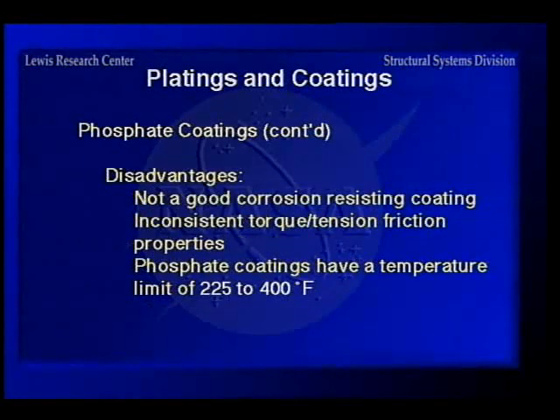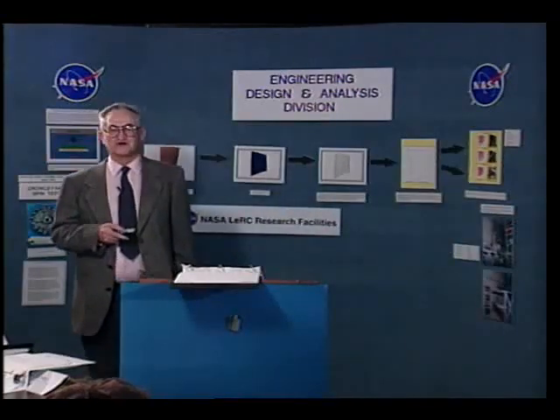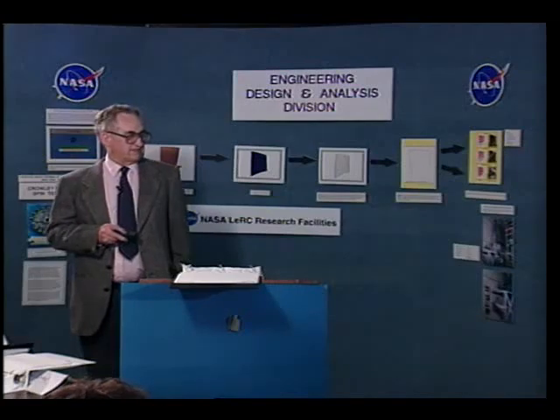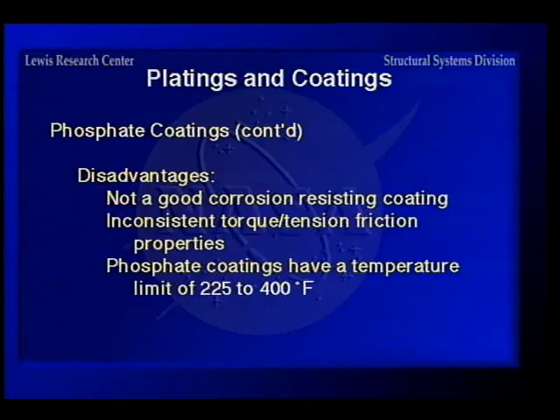But the disadvantage is it's not very good in corrosion. You get inconsistent torque tension friction properties, which means if you are supposed to torque a head bolt to exactly 2,000 pounds tensile load, you don't know what torque it'll take to do it if you have different fasteners that were at a different location in the barrel. And they have a limited temperature of 225 to 400 degrees.